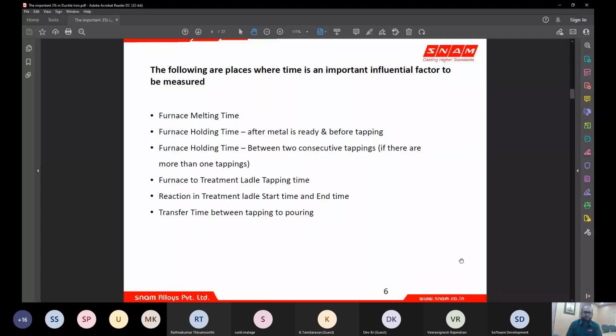And as there is no mixing happening after tapping, after the furnace, this top liquid metal which is going to go to your last box pouring will have a severe impact on your fading and nodularity and residual magnesium also. So this increased tapping time or uncontrolled tapping time or intermittent tapping happening in foundries will have an effect which generally